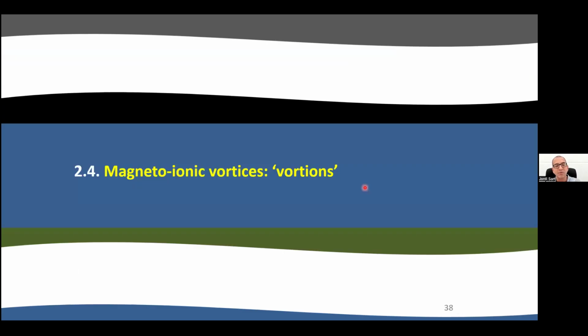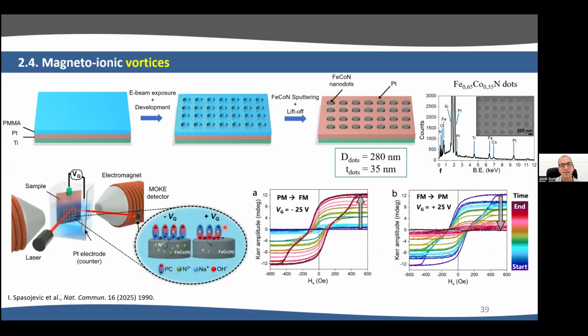Okay, next I want to focus on an application precisely of this planar front. So far, what I showed was continuous layers. What we did next is to pattern the system into small dots. So we used electron beam lithography to create these arrays of iron cobalt nitride dots that initially are paramagnetic. We immerse this sample in the electrolyte, and we measure by MOKE the magnetic properties as a function of time when we were gating, applying minus 25 volt.